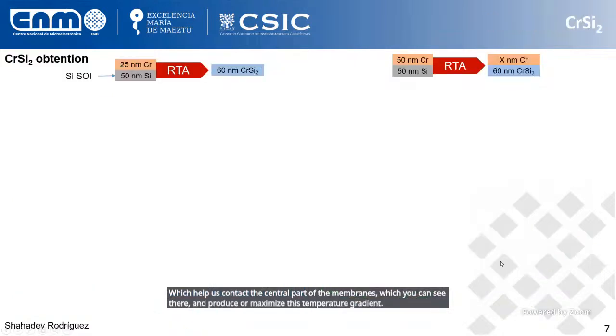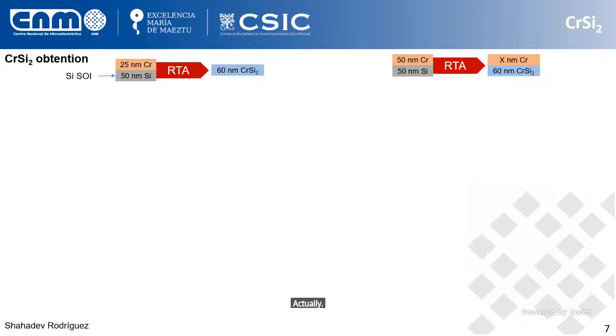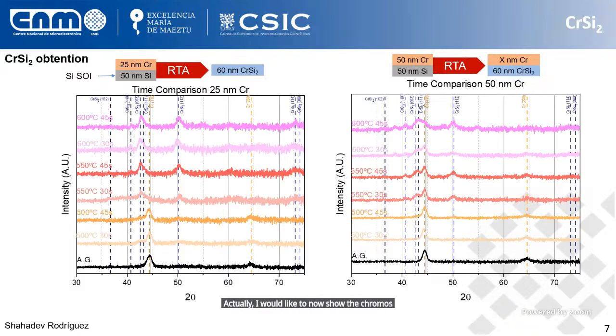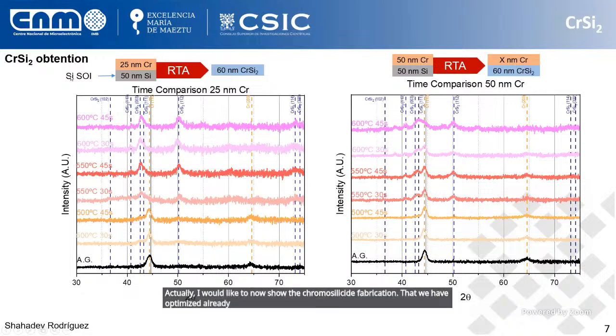Actually, I would now like to show the chromium silicide fabrication that we have optimized already through different RTA processes. In this case, we start with 50 nanometers of silicon from an SOI wafer, where we grow 25 nanometers of chromium. And after different temperatures and times of RTA processes, we end up having 60 nanometers of chromium silicide.